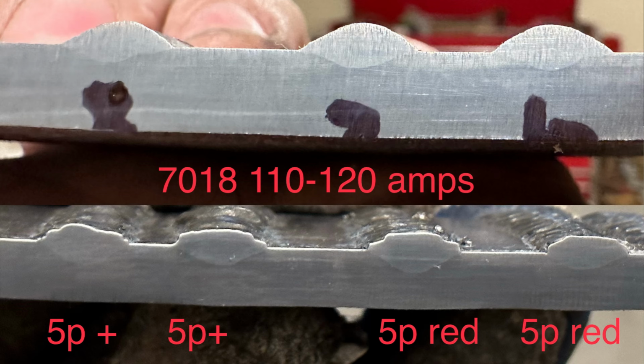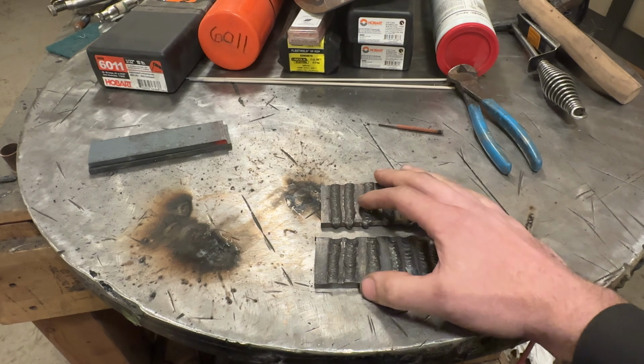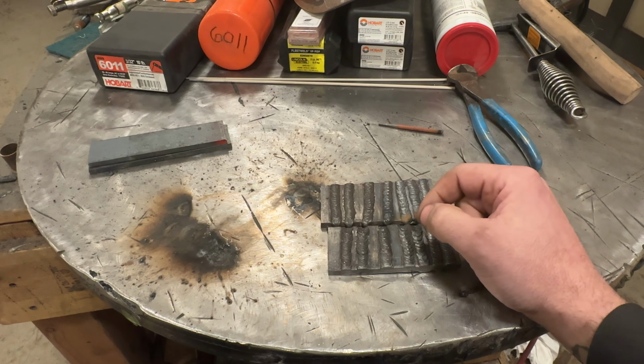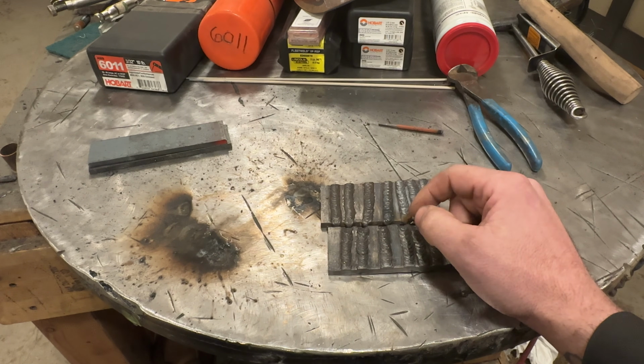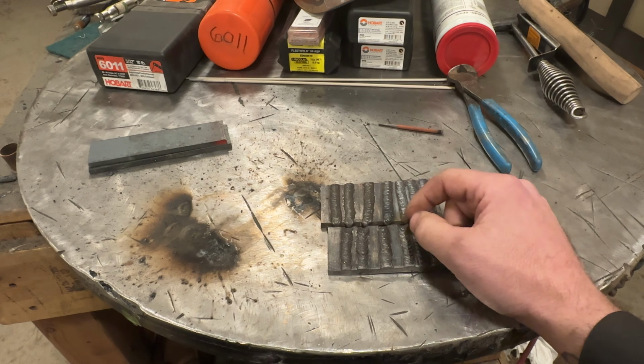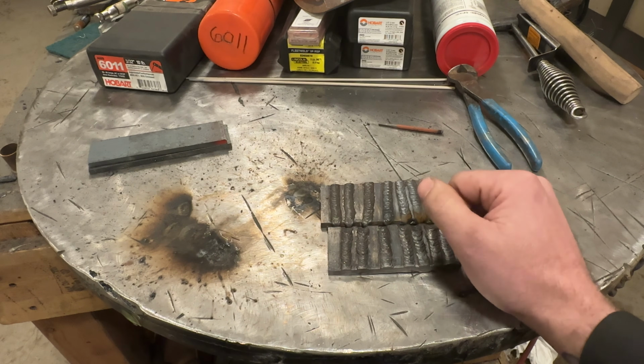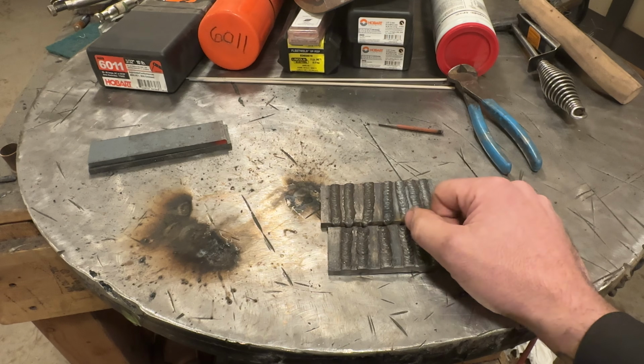When they call 6010 a deeper penetrating rod, it's not just deeper in depth generally, but the overall weld sinks in, chews in better. All right, what did we learn today? Well, we learned that 6011 and 6010 are quite a bit different as far as penetration, and if you don't have your amperage set right, you get none of it, so that's not good.